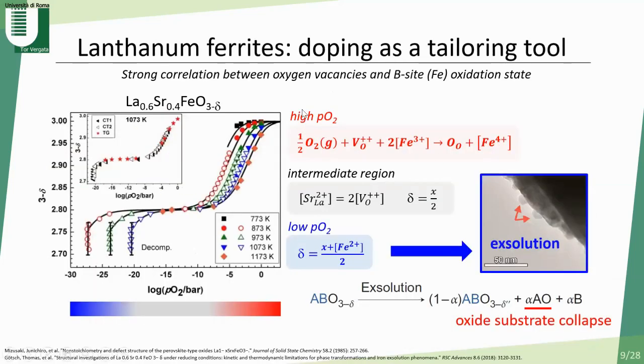Among the most promising perovskite oxides, doped lanthanum ferrites are the most promising. In these compounds, there is a strong correlation between the oxygen vacancies and the B-site oxidation state, as reported in this graph, where we have the oxygen stoichiometry versus different oxygen partial pressure. We see